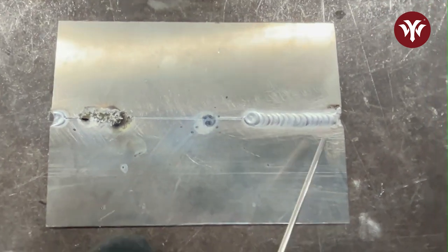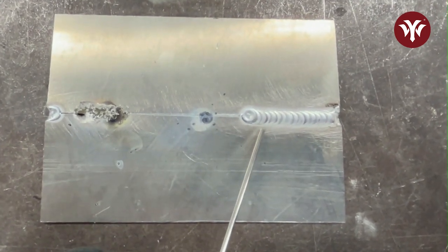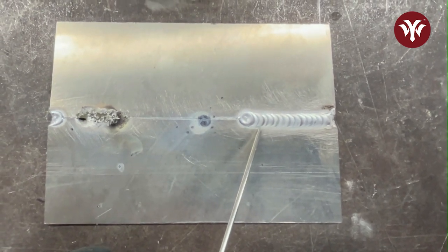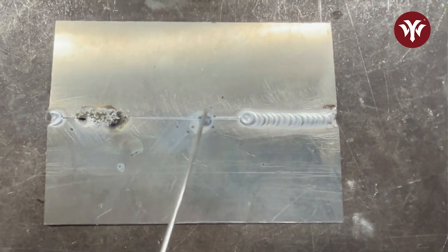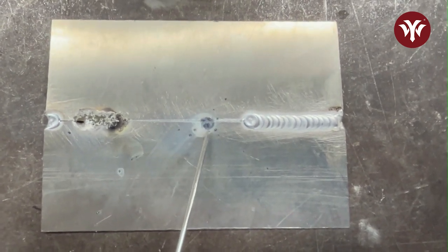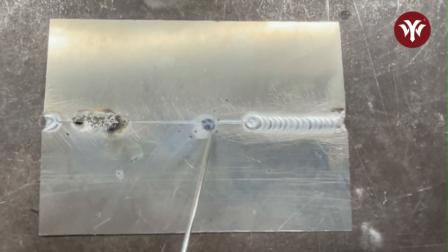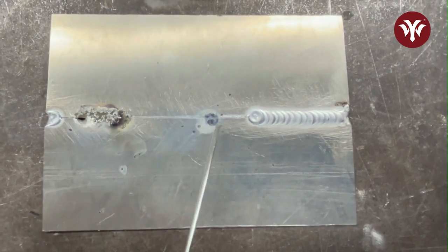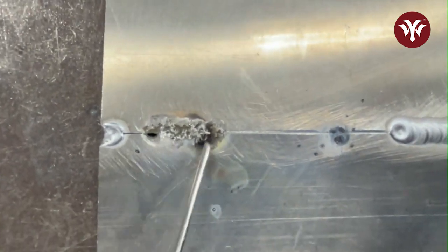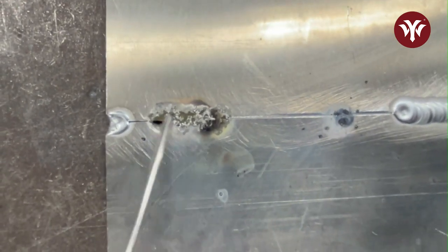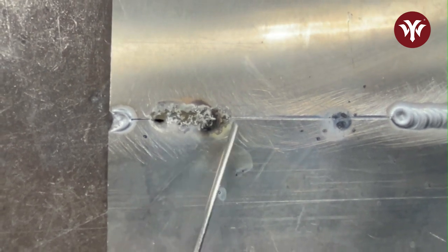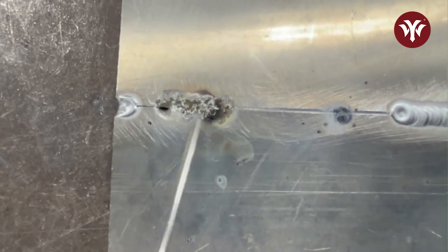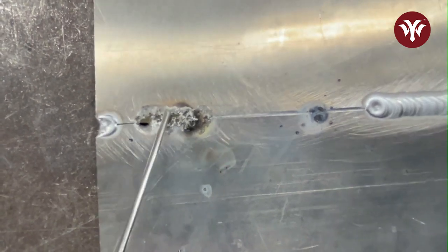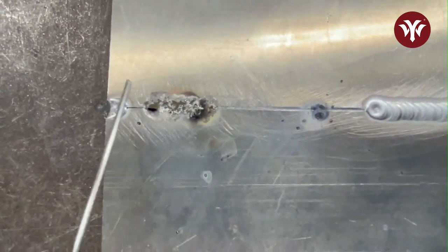Okay, so there we go. Here I laid down a bead for comparison with approximately 12 to 15 CFH because I'm using a number 6 nozzle. In the center, I dialed that back, but it was next to nothing, and it burnt up the tungsten and spit it out and created a lot of black soot. So then I turned up the gas just a little bit more, and you can see what happens here. It melts the material, but it has no cleaning action really, because there's atmosphere pouring in, and it's just gonna create a completely sooty, it's just gross.